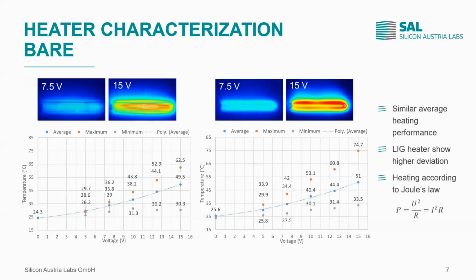On the top pictures, you can see the thermography images of the printed heater on the left side and the LIG heater on the right side. As you can see on the plot, both heaters show similar heating behavior, with a quadratic dependency of the heating power on the applied voltage according to Joule's law. The only main difference here, I would say, is that we have seen bigger deviations of the average temperature value in the case of the LIG heater, which is probably due to a more inhomogeneous surface of the heater itself.